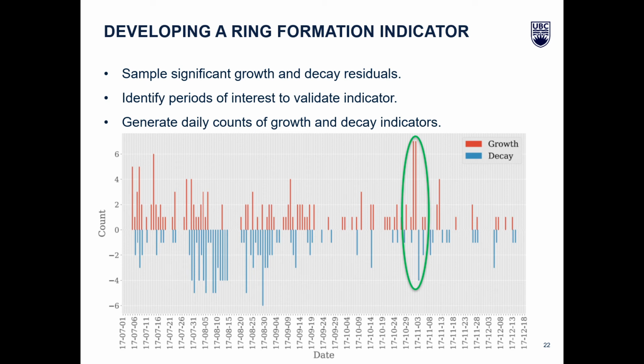This slide demonstrates the ring indicator that is developed by sampling significant growth and decay residuals that are not extreme outliers. The figure shown here illustrates one approach to using these significant residuals to create a ring indicator. By sampling from the significant range of positive residuals, we obtain a set of ring growth residuals that span the experimental trial. The same is performed for the significant range of negative residuals to obtain the ring decay residuals. Once these two sets of residuals are sampled, we assign them equal importance by throwing away their magnitude information.